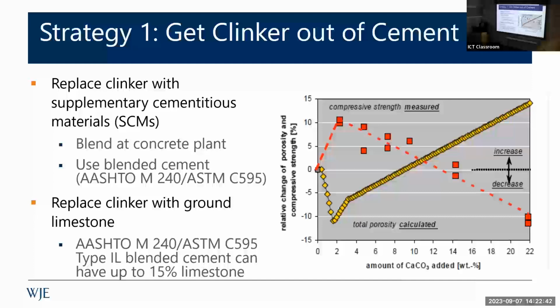I don't have a lot of slides on the science of this. This is an overarching practical talk, but the bottom line is if you study this and you couple this with clays or aluminate sources from an SCM, you'll actually get another phase formation, carboaluminate formation, and you get a synergistic relationship. So when you take a blended limestone cement and you blend it with a fly ash with high alumina, or slag, or a calcined clay, you actually will see added benefit.